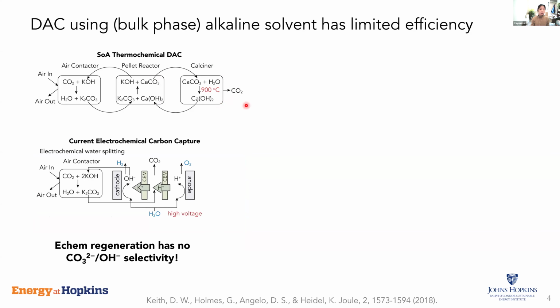And a lot of scientists are trying to replace the thermochemical method with electrochemical regeneration of potassium carbonate into potassium hydroxide. So the idea is to use an electrochemical method to generate protons, either through hydrogen oxidation or water splitting or some other equivalent method, so that the proton can react with potassium carbonate to release carbon dioxide, followed by the simultaneous generation of hydroxide to regenerate our alkaline sorbent.